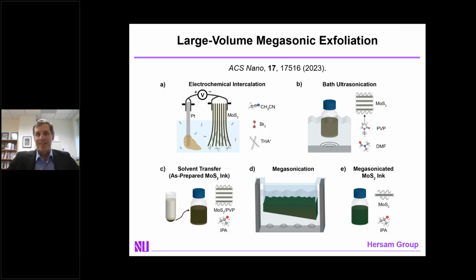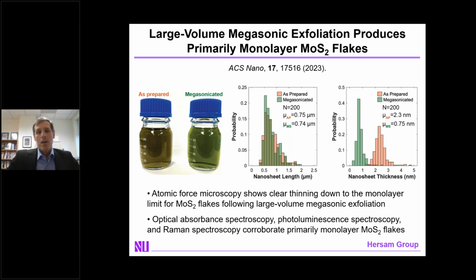The last step is then to ask, can we scale up the megasonication process? This is work in progress. But what we've employed are megasonication baths, which are widely used in the semiconductor industry. We've been able to achieve the same level of exfoliation that we achieved using the small aerosol jet printer atomizer. The resulting flakes are quite nice. They're showing clear evidence for monolayer thickness in atomic force microscopy, photoluminescence spectroscopy, and Raman spectroscopy. These inks are giving us suitable performance in photodetectors, and I think puts us on the brink of now taking this to the commercial scale.